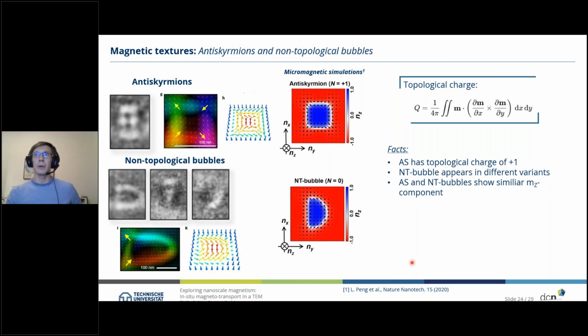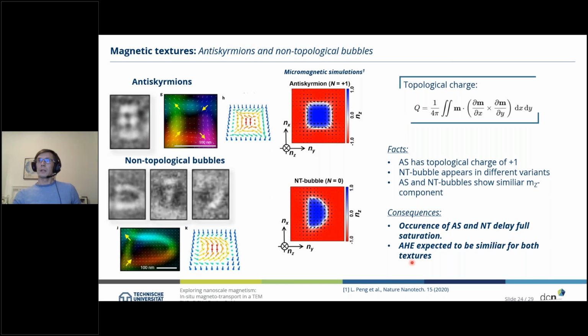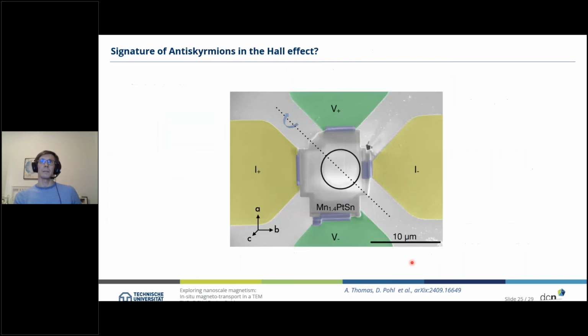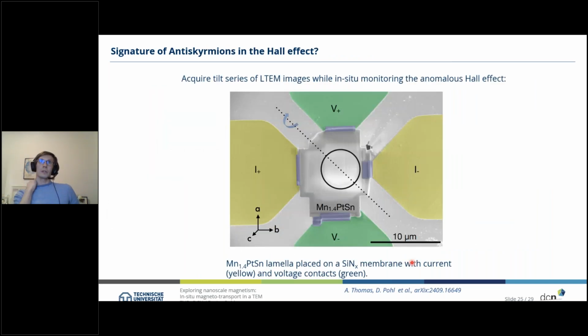So how can we set up now an experiment to measure an impact on the topological Hall effect of these different magnetic textures, since the anomalous Hall effect seems to be similar in strength, since the out-of-plane magnetic component is the same. So what we thought of was to acquire a so-called tilt series, where we tilt the sample along that dashed line here. And by doing so and keeping the objective lens at the same value, we will have a change of the in-plane magnetic field, and that will transform anti-skyrmions and non-topological bubbles into each other.